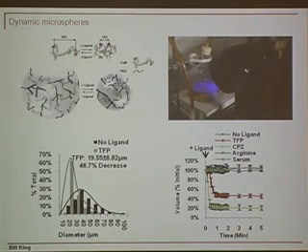But then the big question is whether or not these particles will undergo the same kind of shifts that we've seen with the bulk hydrogels I described earlier. And they do. So if you look at distributions of particles before application of trifluoperazine and then after application of trifluoperazine here in gray, what you see is about a 50% decrease in volume of these microspheres, and this can be tailored based on the amount of calmodulin in the network.